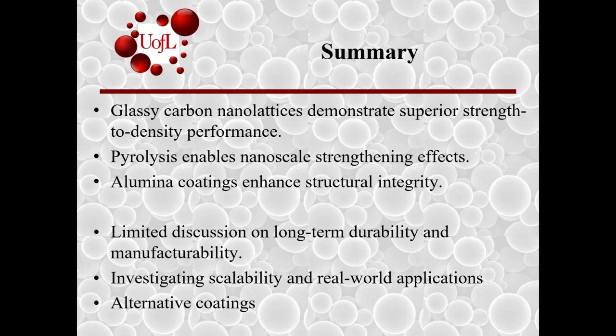The final material selection of glassy carbon nanolattices was made due to their unmatched strength to density ratios achieved through extreme miniaturization and optimized architecture. By minimizing the flaw size below 30 to 70 nanometers, these nanolattices approach the theoretical strength limit of bulk glassy carbon. And by considering honeycomb topology that further maximizes load distribution and alumina coatings that provide enhanced buckling resistance, these combinations of lightweight design, high specific strength, and flaw insensitivity make glassy carbon nanolattices the optimal choice for applications that require maximum strength at minimum weight.